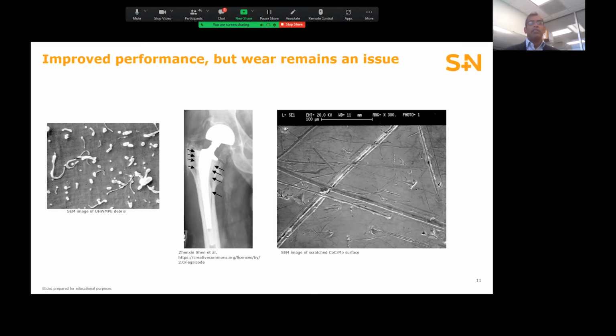So while the introduction of polyethylene greatly increased the life of hip replacement devices, the failures that did occur were often due to loosening. This loosening was caused by cellular response to debris in the joint space. While the initial response is inflammatory in nature, involving macrophages, a subsequent cascade of reactions ultimately impacts the natural bone remodeling process, resulting in bone resorption or osteolysis.